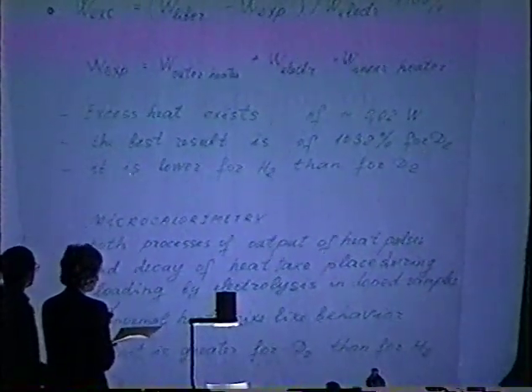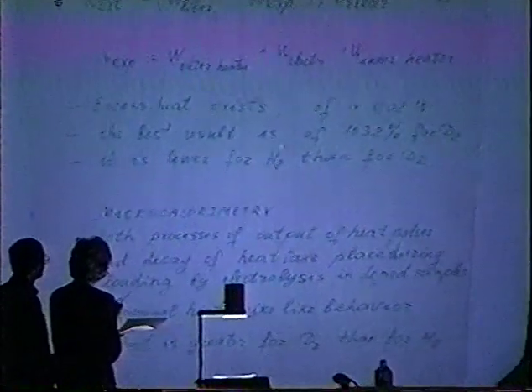Of the order of 0.02 watts. The best result being 1032%. These effects are lower for hydrogen than for deuterium.